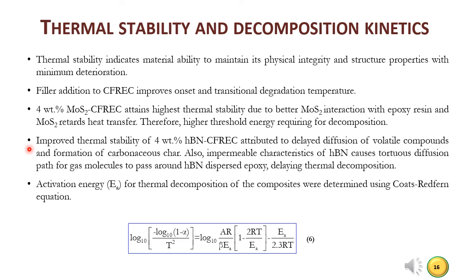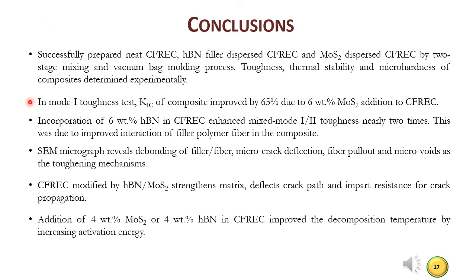65% improvement in mode 1 stress intensity factor is witnessed due to 6 weight percentage MoS2 addition. 6 weight percentage hBN addition to CFREC exhibited 2 times improvement in mixed mode stress intensity factor. Toughness improvement was due to hBN and MoS2, which strengthen the matrix, deflect crack path, and impart resistance for crack propagation. Addition of 4 weight percentage MoS2 or hBN in CFREC improved decomposition temperature by increasing activation energy. The developed hybrid composite has multiple desirable properties useful for high performance applications.